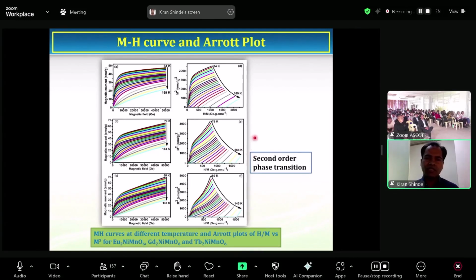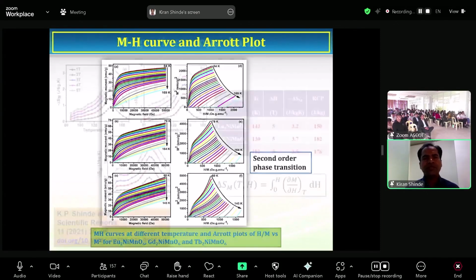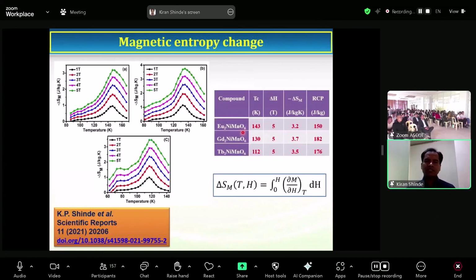So we confirm that this prepared material is showing second order phase transition, which can be useful for practical applications. In this slide, we can see the magnetic entropy change for this studied compound, denoted as delta SM in joule per kilogram Kelvin on the y-axis, and temperature on the x-axis. We calculate these magnetic entropy change values using this formula.